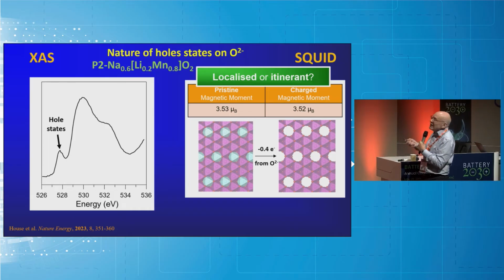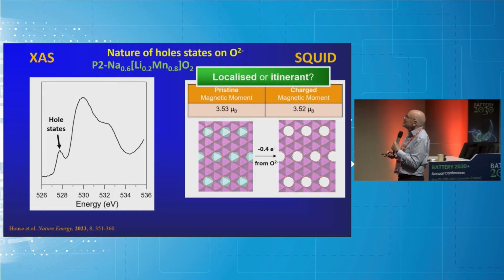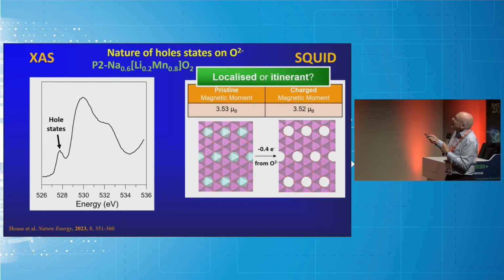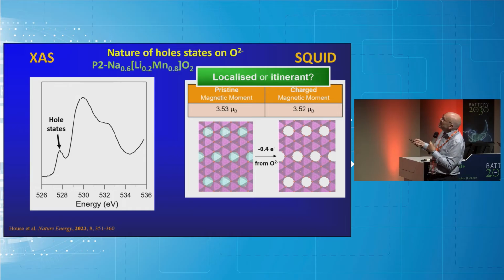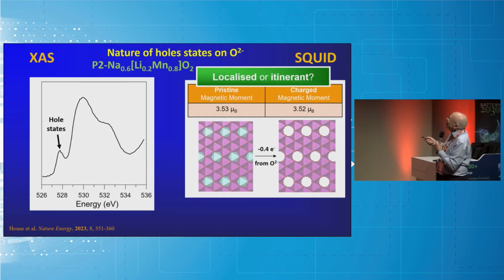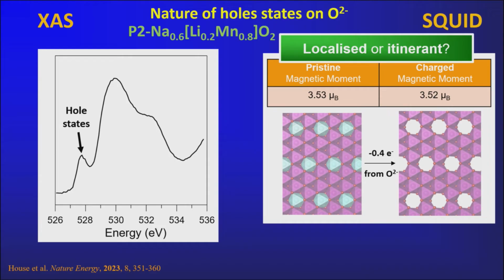And again, we can look at magnetism to confirm this. Here's the magnetic moment for the pristine material. Here's after charging, after we've removed sodium, oxidized the oxide ions. We've oxidized 0.4 electrons per formula unit, so quite a lot of oxidation. No O2 formation. We have the same magnetic moment after charging. So if we were forming O2 with all those unpaired spins, we would see a change in the magnetic moment.